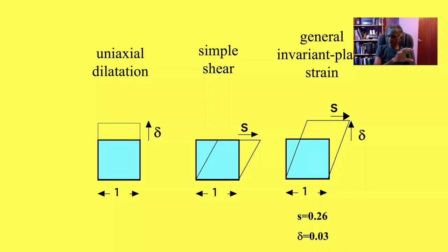Okay, we can measure these shape deformations in a variety of ways, for example, by the deflection of scratches, by using optical interference microscopy, or using the atomic force microscope or scanning tunneling microscope to look at the surface topography and the crystallography underneath. I want to explain to you in some detail the nature of the shape change accompanying martensitic transformations.